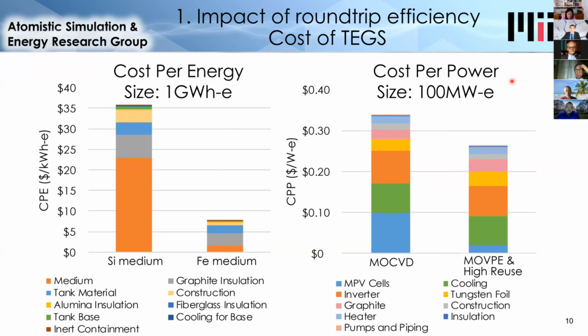Going on to the other plot, which is the cost per power, this is primarily the heat engine, the conversion from heat to electricity, which is in this case photovoltaic cells. The cells themselves are the cost in blue at the bottom, which are relatively low, not because the cells are inexpensive, but because the power density is so high. So essentially, this would be like putting a solar panel very close to the sun, where the heat has not diffused away into the low intensity that we have at the Earth. And so these photovoltaic cells generate electricity about 1,000 times more compactly than existing photovoltaic cells. So while they're expensive, you don't need as many of them. The other important costs are cooling the cells and converting from DC to AC electricity.